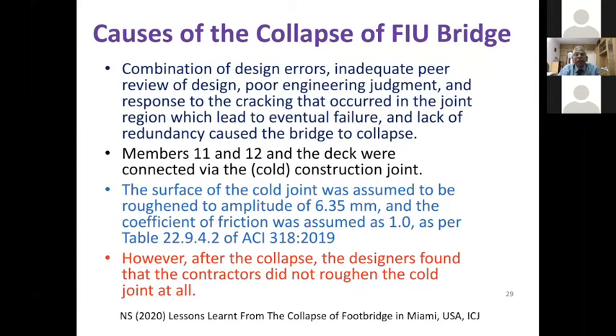a combination of design errors, inadequate peer review of the design, poor engineering judgment, and response to the cracking that occurred in the joint region, which led to eventual failure. The lack of redundancy caused the bridge to collapse. Actually, when there were cracks, the people in charge of the bridge at the site never bothered because it's a pre-stressed bridge. They thought that by pre-stressing, the cracks would disappear.